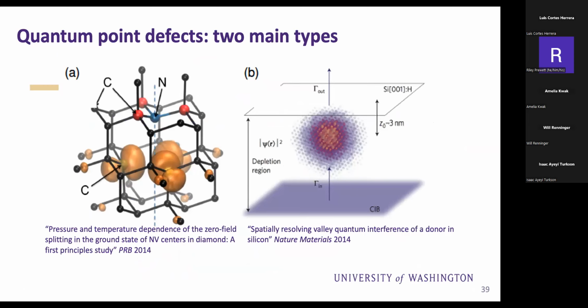Okay, so you can broadly separate defects into two categories. One is very deep, super spatially well localized. By deep, I mean deep within the energy band of the crystal, the semiconductor, very well localized defects, such as the nitrogen vacancy center in diamond that you see over here. And then you can also have very shallow potentials for carriers. And over here on the right, you see the wave function reconstruction from a scanning tunneling microscopy measurement of a single phosphorus in silicon. Here you're looking at the density of the electron, psi squared, and you can see that it extends over many, many lattice sites in this case. So this is an extended shallow donor.